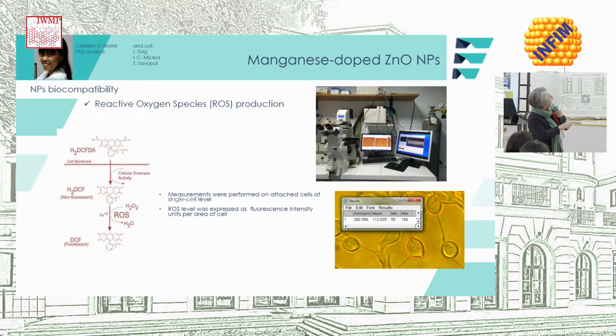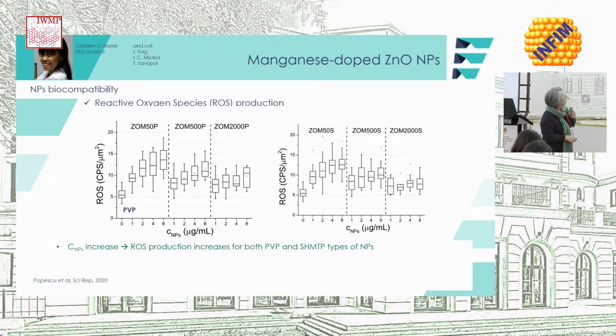Then Christian measured the ROS production using attached cells with a DCFDA product, which, once inside the cell, is producing a compound which is fluorescent. And this fluorescent intensity she normalized to the cell area. So it was a single cell type of measurement, but normalized to the cell area. And she obtained these types of graphs of ROS production with respect to the concentration of the nanoparticle. And we can see that once the concentration of the nanoparticle is increasing, the ROS production is also increasing for both types of surfactants.